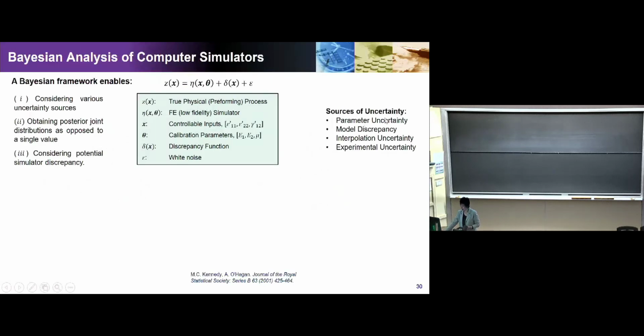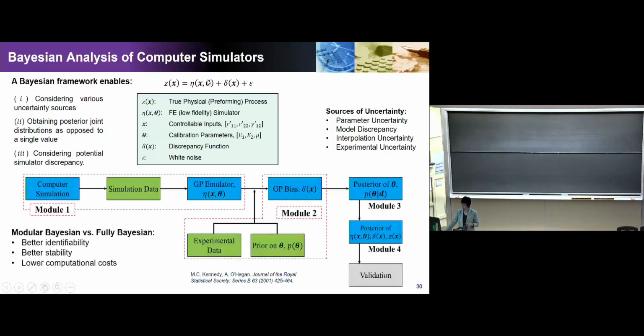The approach we're using, some people probably know, is the Kennedy-O'Hagan approach. It basically says that the experimental data is equal to the model prediction plus some bias function plus some physical experimental error. So the unknowns here include both theta and the bias function. The bias function tries to capture the model error. That's the difference between our work and a lot of existing work on model calibration: they take away this delta, only look at theta, and lump all the uncertainty into theta. We put them as separate quantities to quantify uncertainty.